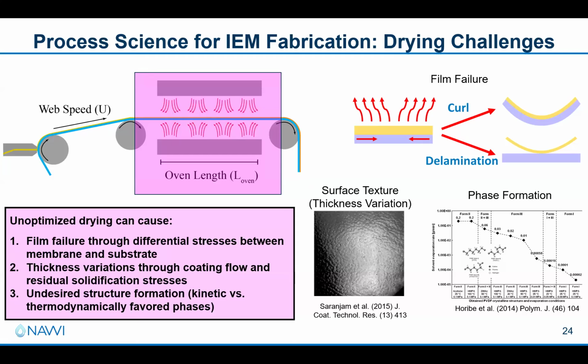So just as an example, whenever we're drying a coating, there's always going to be some shrinkage of the coating as it solidifies. As a result of that shrinkage, stresses can develop within the coating. This can happen whether you're working with a system that solidifies via solvent evaporation. It can happen with systems where you're UV curing as well, because there tends to be a lot of shrinkage related to the curing process.